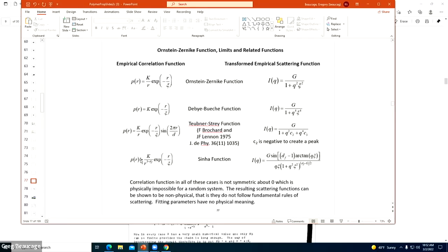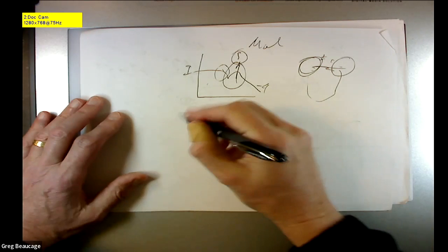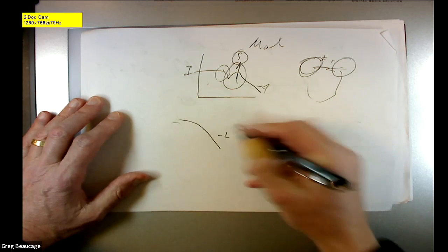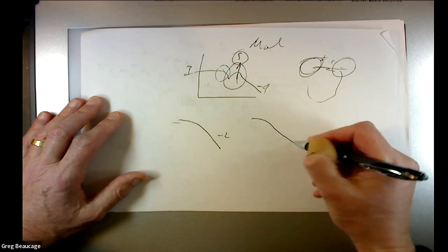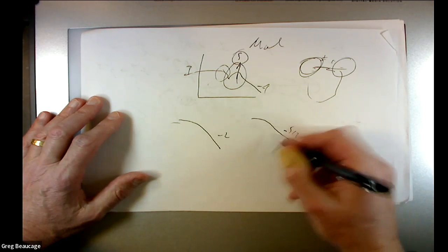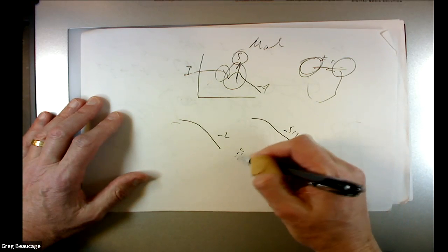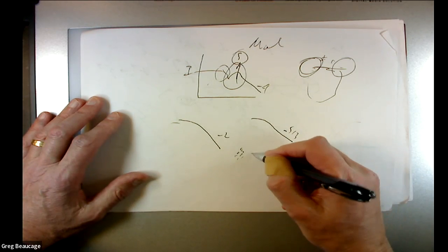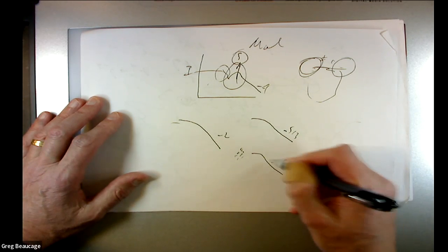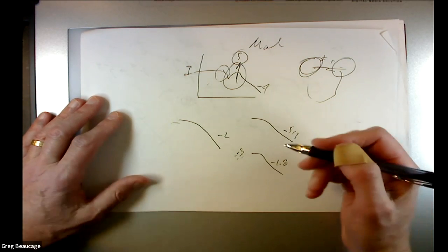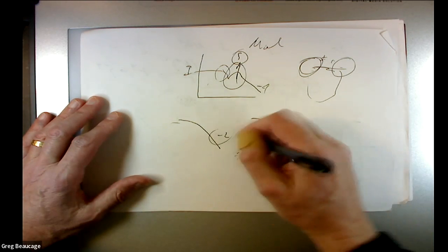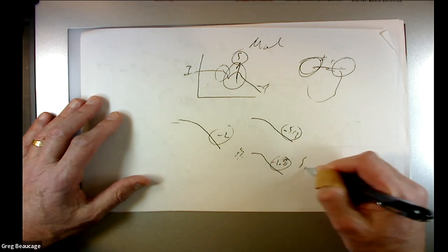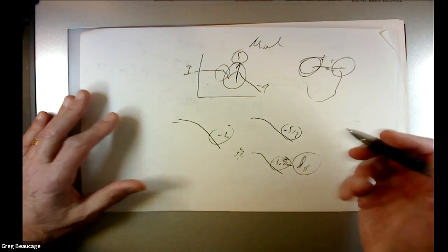Sinha said you can have the Ornstein-Zernike that can make this -2 thing, but in a good solvent it's -5/3, or for a fractal aggregate like dust, you get -1.8 for diffusion limited aggregates. These are the fractal dimensions, so you want some arbitrary DF for this thing.